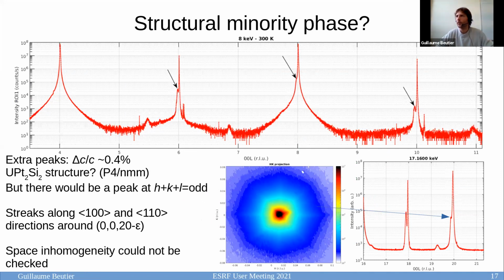Another thing that was interesting, which we saw by X-ray diffraction at the synchrotron, is that we saw some additional peaks that were not expected. If you look at this L scan here, you can see that there are small shoulders appearing beside the main peaks. These shoulders are consistent with a phase which would have a C lattice parameter 0.4% larger than the main phase, but it grows coherently with the main phase.